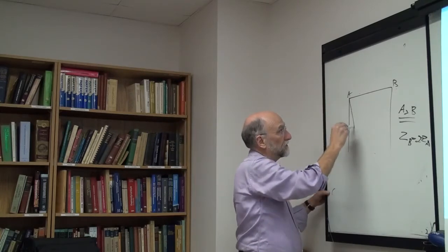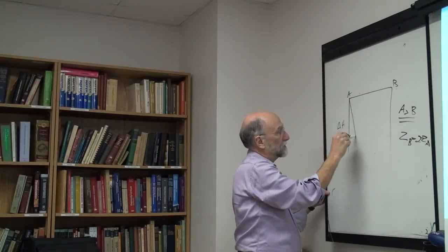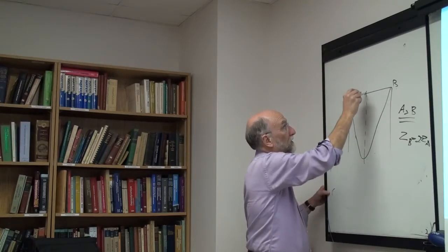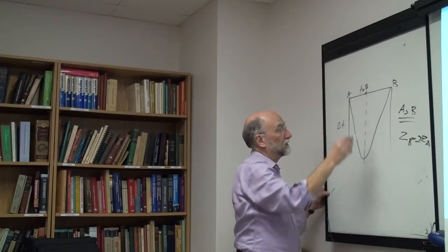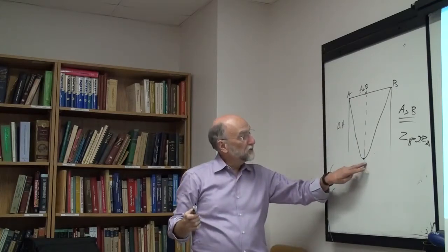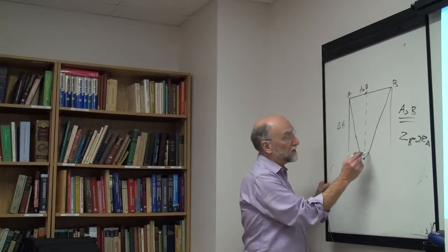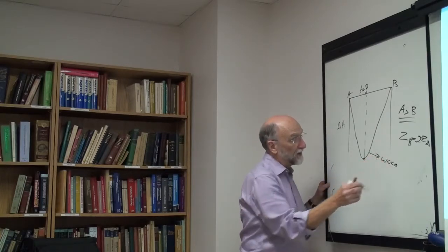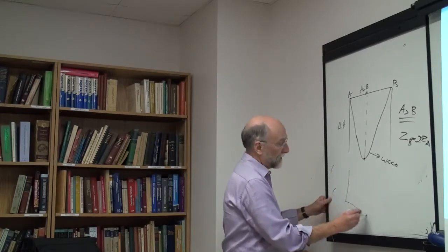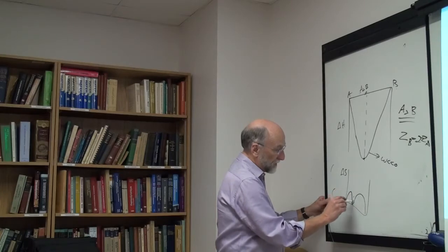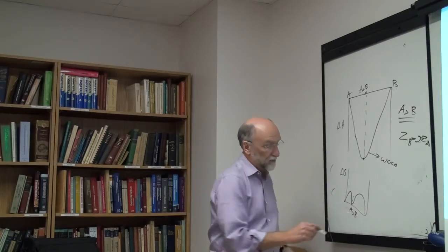The heat of mixing is going to have a very sharp peak, and the peak is going to be very close to the A2B composition, because at A2B composition all A's are surrounded by B's, and virtually all B's are surrounded by A's. If omega is very negative, it's very strong ordering. Similarly, the entropy expression is also going to come down like this and be ordered around the A2B composition.